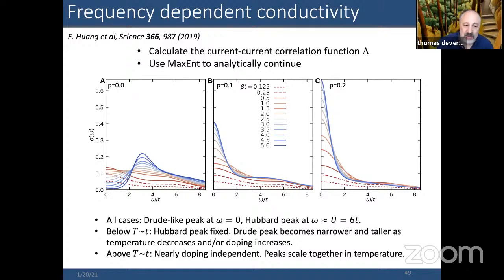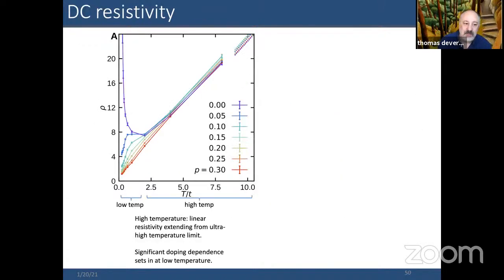So if I just plot one over that DC value to give a value of the resistivity, here's a broad window in temperature for different dopings, up to 30% doping. And of course, at very, very high temperature, given we have a finite band, it's not a surprise that rho should go linearly with T. That's what the dashed lines are there. And then of course, at very, very low temperatures, at half filling, it's an insulator. So the resistivity blows up as the gap opens up.